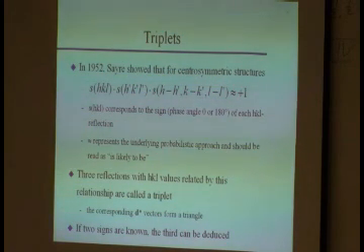It looks like a very simple, trivial equation, but this part that comes from probability actually allows you to assign phases to all reflections. Okay? Because once you've assigned a phase to one of these by knowing two of the strong ones, you can use that one as an additional part of your basis set. You can keep going, so you can assign phases to all reflections. As I said, these are called a triplet, and their corresponding D star vectors will actually form a triangle, so that's where the triplet comes from. If you know two of the signs, you can figure out what the third one is.